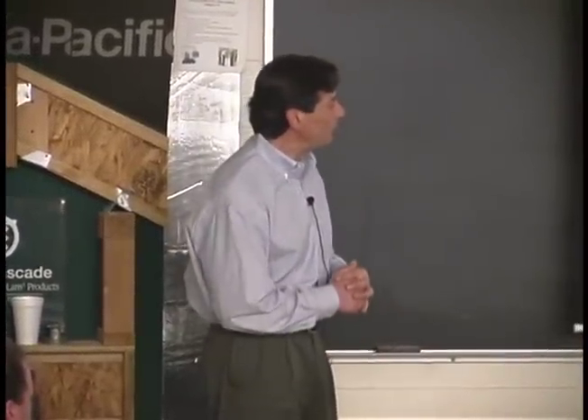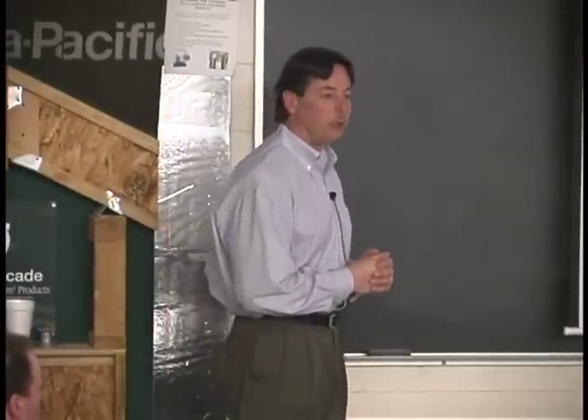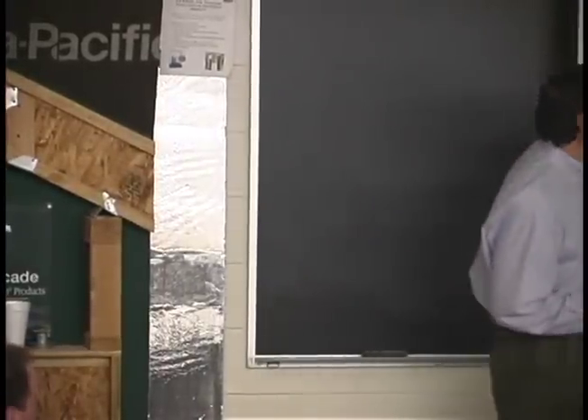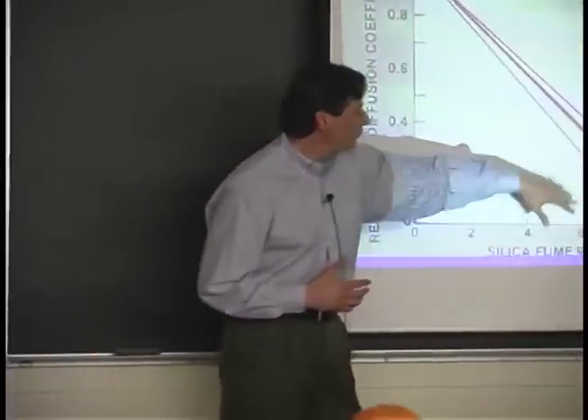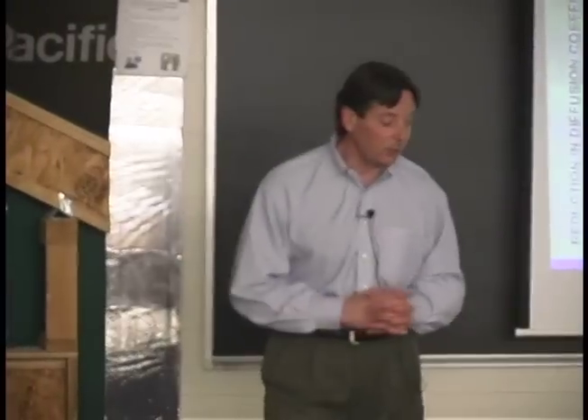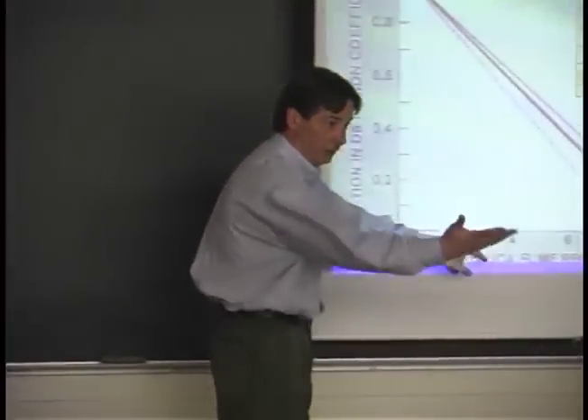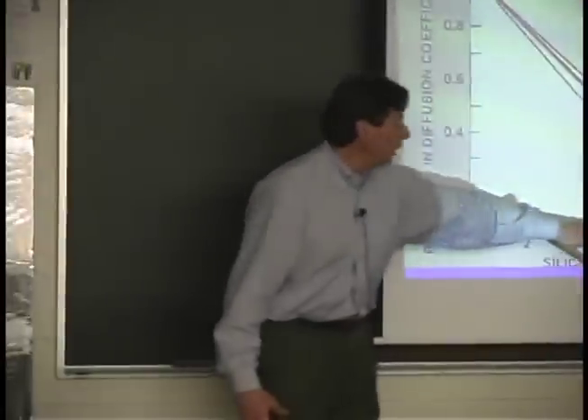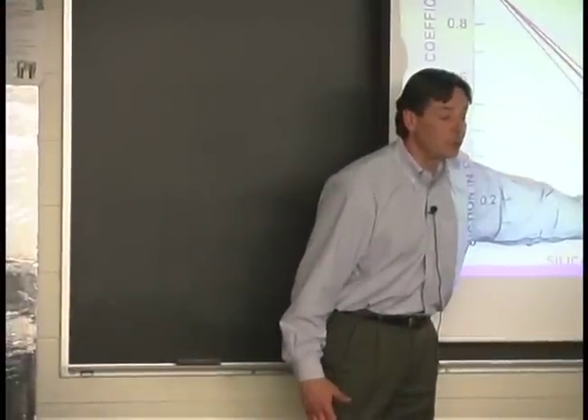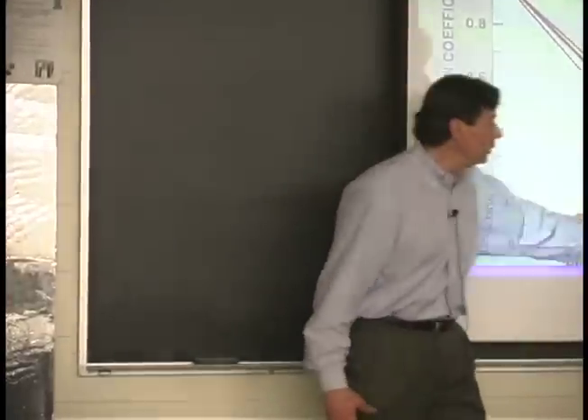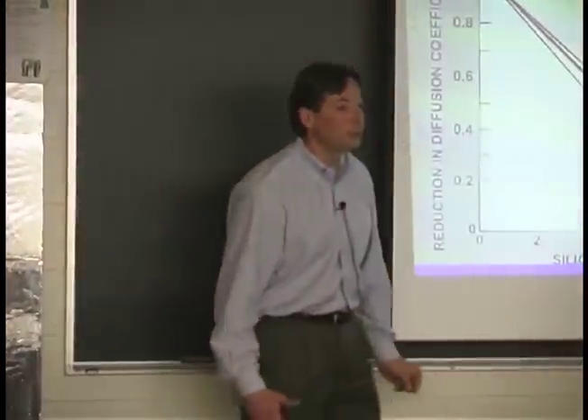All those different values there are different permeability tests that people run on concrete. This is just a way of comparing all these different test methods, and they more or less show the same type of trends. So it takes very little of this particle packing to get the biggest impact. As you see, you have a point of diminishing return here at about 7%. From here on out, as a cement replacement, you're only producing strength.